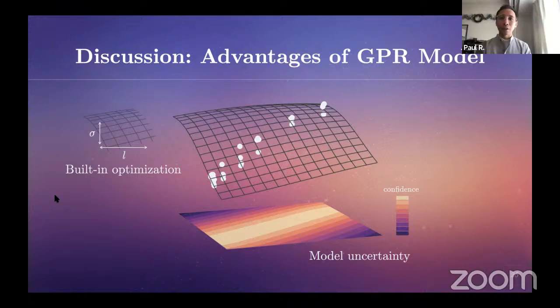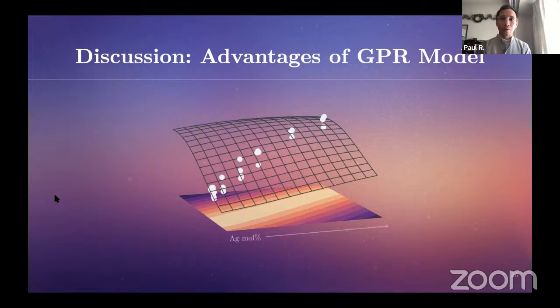This information is crucial for high-risk problems such as predicting nanotoxicity because model predictions can have real-life impact. And capturing model uncertainty is a careful approach to such problems. Not only that, because GPR informs us with its uncertainty, we can use that information to direct our next lab experiments. For example, in our current model, we can see that the model is not confident in this area. But this area is where Ag% is the highest, and yet the model predicts EC50 to be lower.